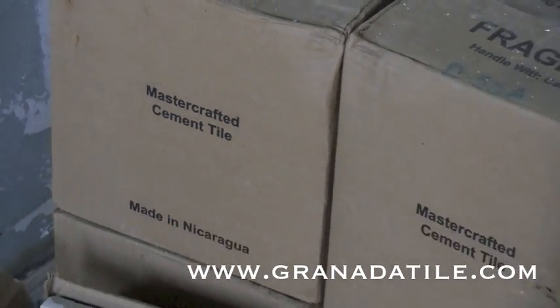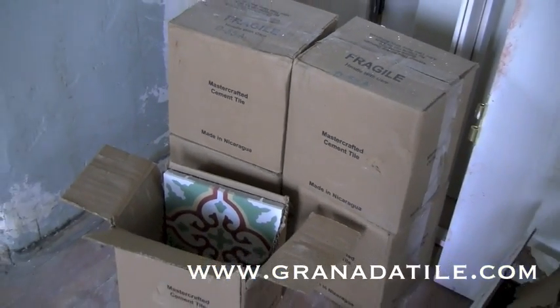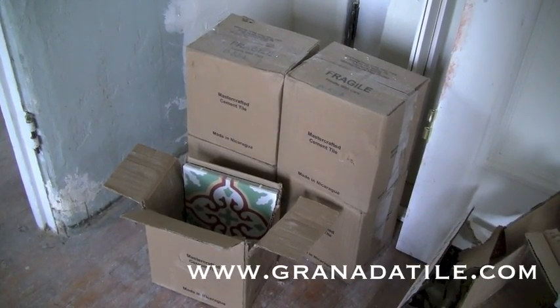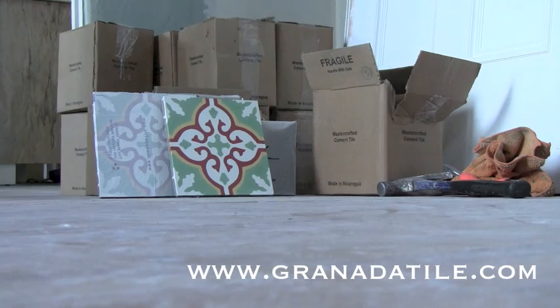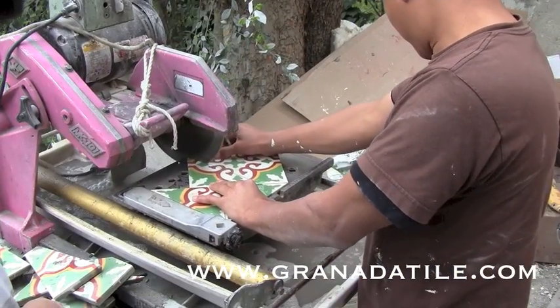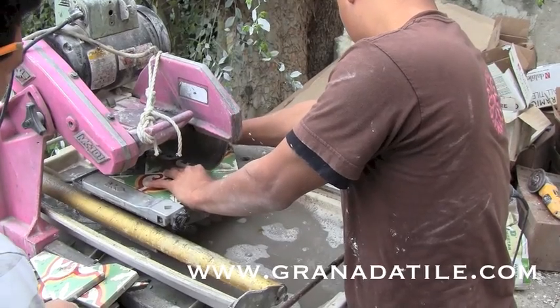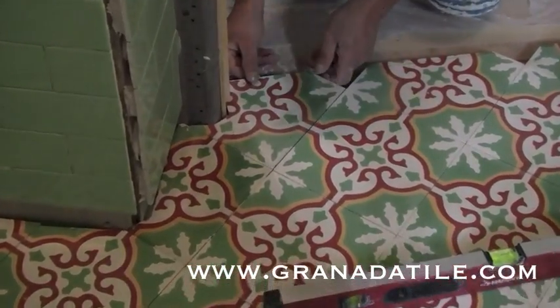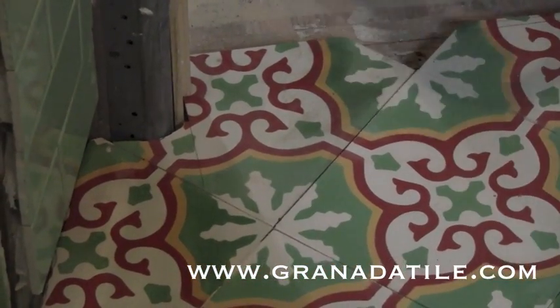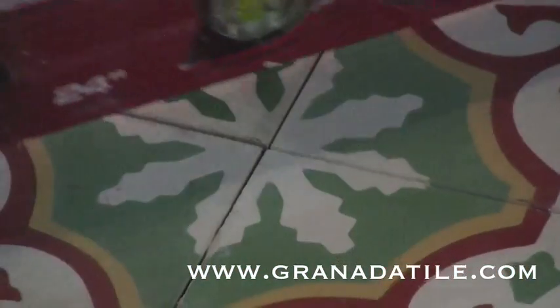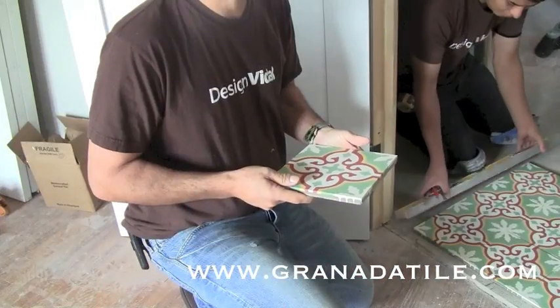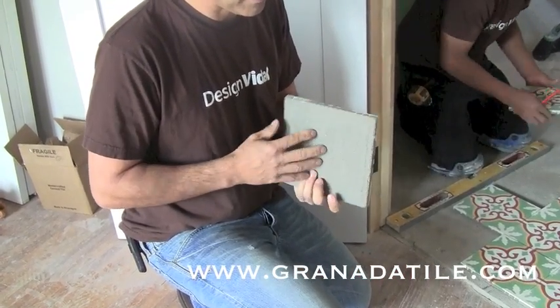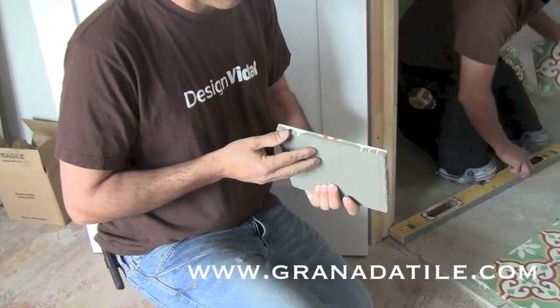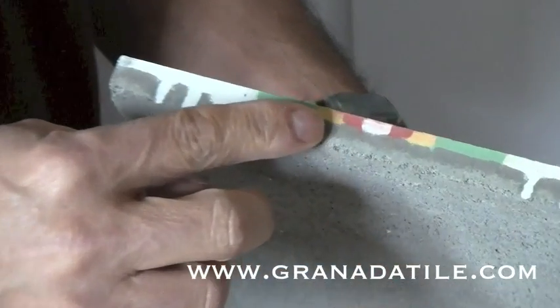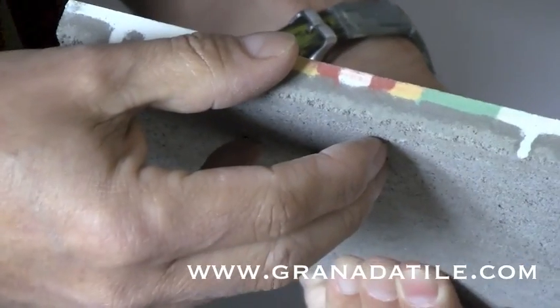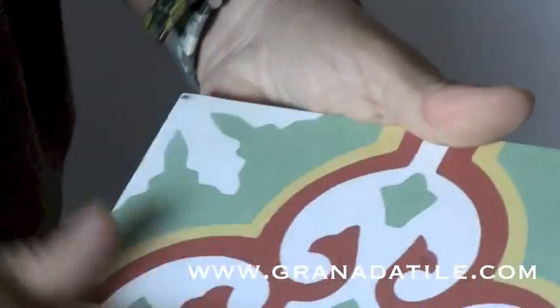On large jobs, we recommend mixing tiles from different boxes so as to ensure that there's an even distribution of shade. This type of tile, because of the nature of cement and because of the natural pigments that we use, does vary in shade, and that's just part of the process and part of the beauty of the product. Unlike glazed tile or porcelain tile, this product is raw cement. It's not fired in a kiln, and it's encaustic, meaning that the color is actually part of the tile. So it's very important that this raw product be sealed.